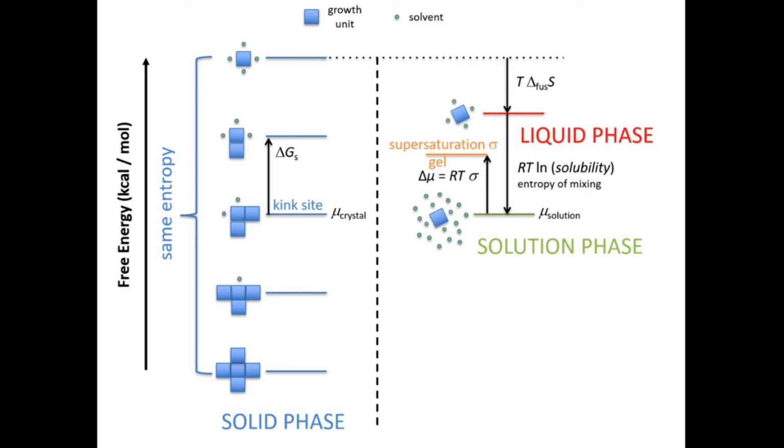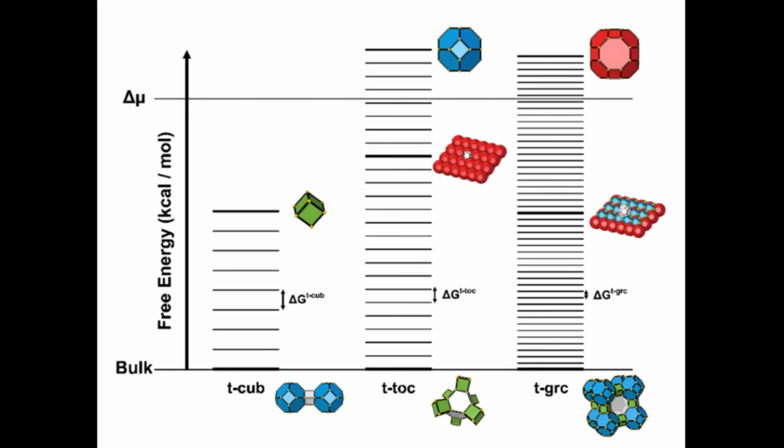However, the situation is different for a tile type structure, and here for example is an energy level diagram for zeolite A, where there are three different cage types, and in this particular case what we're doing is something quite different, because here we are looking at the energy of condensation of vertices on particular tiles. So in this particular case, the zero state here is where we have everything in a Q4 state.